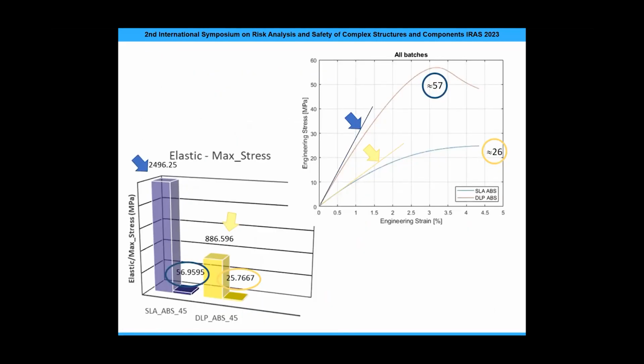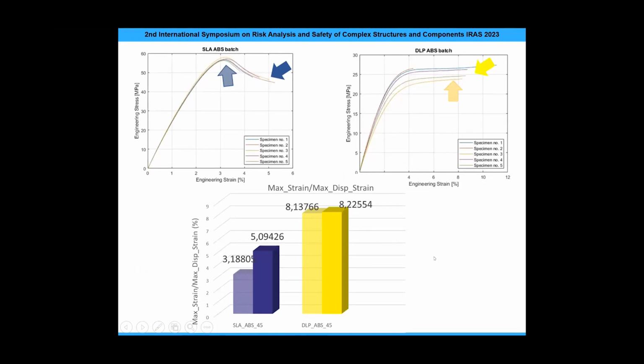In more detail, we can compare the elastic modulus for both. This is the average curve for SLA and the average curve for DLP specimens. The elastic modulus is quite different: it is about 2,500 for SLA and almost 900 for DLP specimens. And there is a difference in the maximal stress, around 57 megapascals for SLA and around 26 megapascals for DLP. Additionally, if we compare max strain and elongation to break, you can see the difference. There is a quite different value for SLA and a very similar value for these 2 parameters for DLP. So we can say it is a more durable material if we print specimens using the DLP technique.